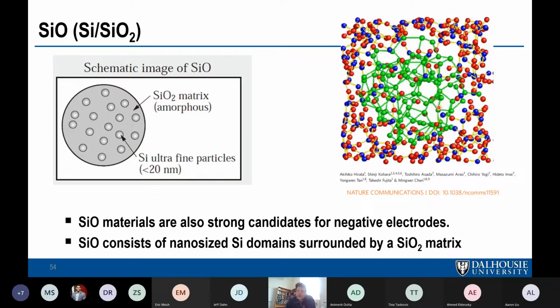So you have, by virtue of this structure, pure silicon that might be bonded to 3 silicon and 1 oxygen, all the way up to silicon bonded to 4 oxygen in SiO2. So SiO is a distribution of silicon bonded with pure silicon all the way to all oxygen around the silicon. But the basic structure is like this.